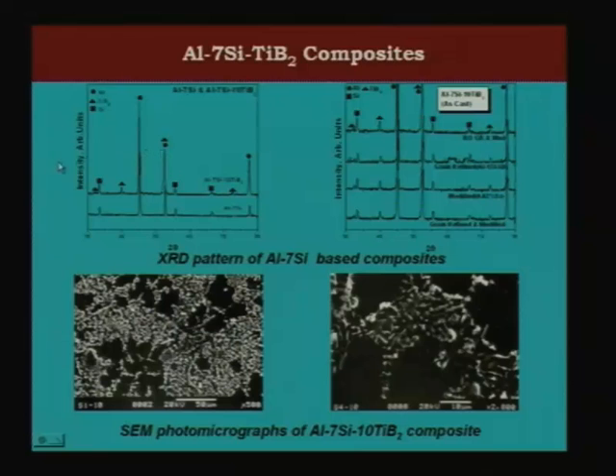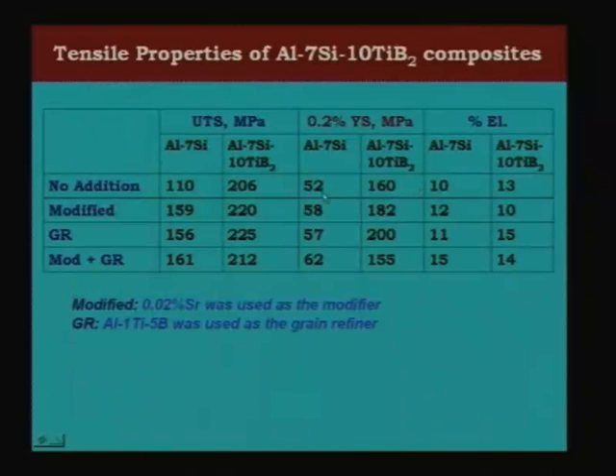From the XRD pattern one can see that one can do grain refinement of the aluminum 7 silicon alloy and do modification so that one can have an improvement in the properties. We will try to see what kind of improvements. The improvements are not really as dramatic as in the case of aluminum copper, because aluminum copper is an age hardening system, one has to remember that, whereas aluminum silicon is not an age hardening system.